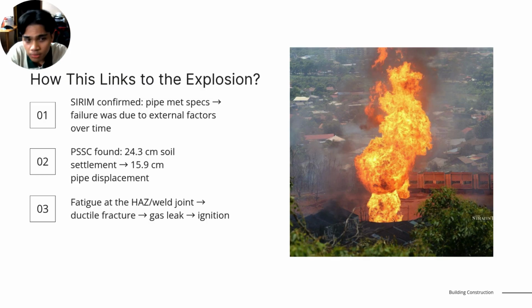So how do all these material properties connect to the actual explosion? Since SIRIM already confirmed that the pipe met technical specification before the construction, it suggests that the metal itself wasn't defective. The real cause was long-term fatigue. The PSSC found that the soil settlement has caused the pipe to undergo a displacement, which caused the stress concentration right at the weakest point, which is the HAZ of the welded joint.